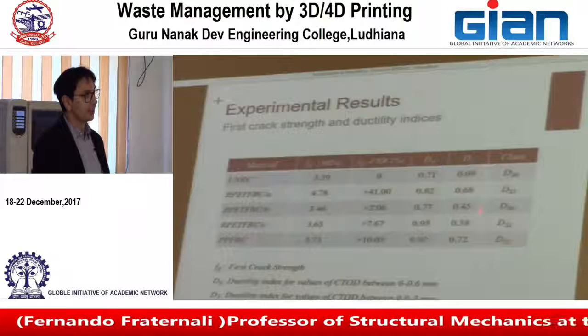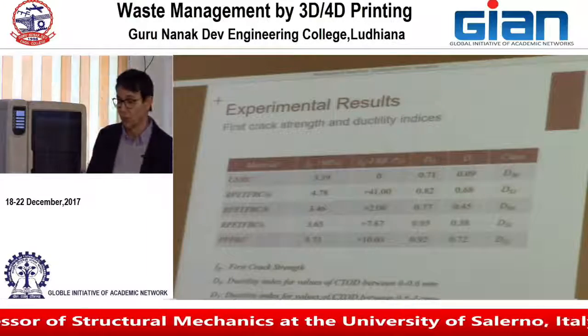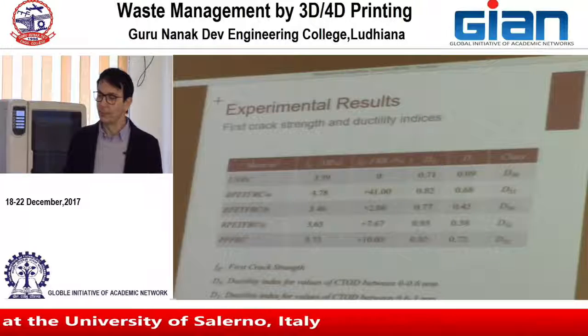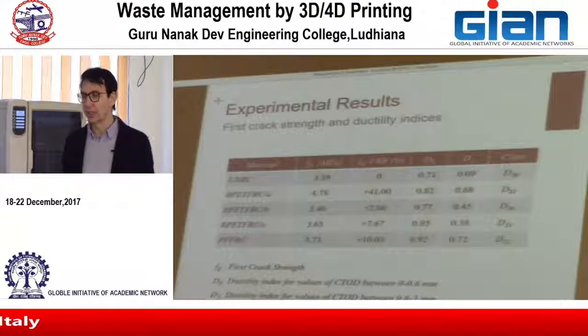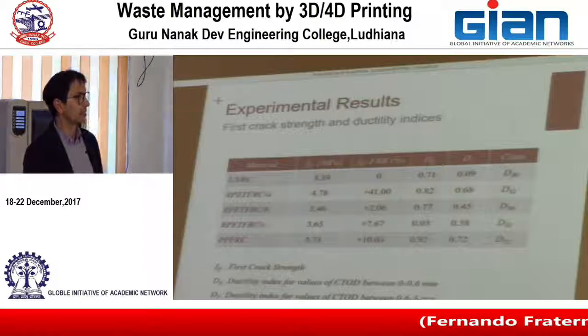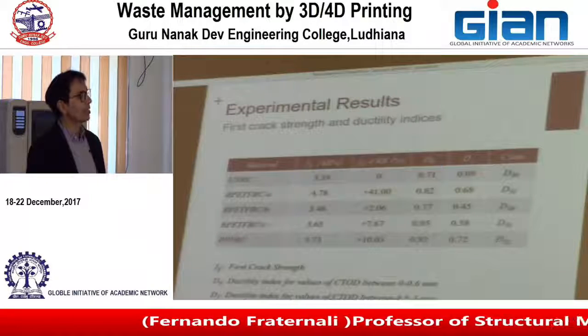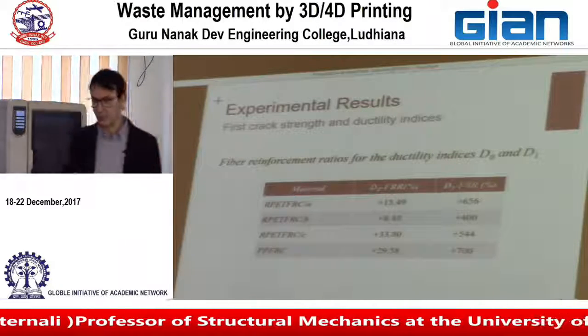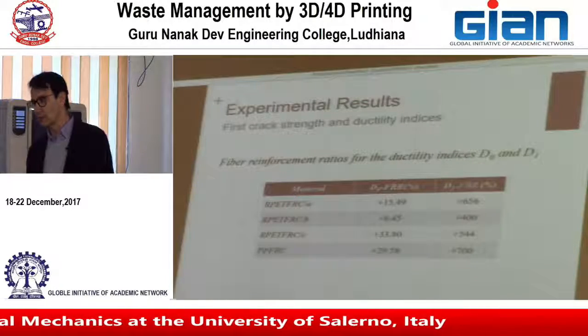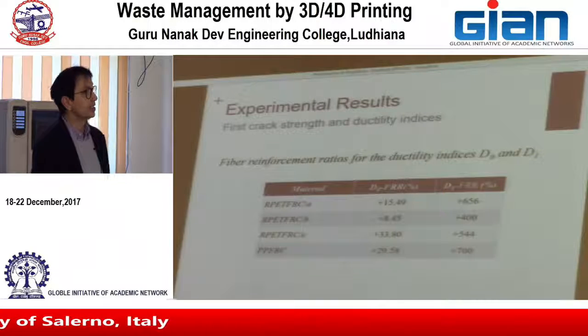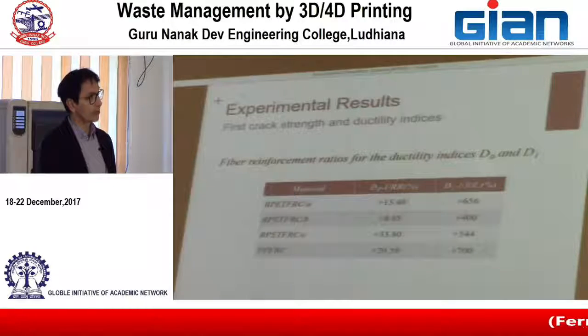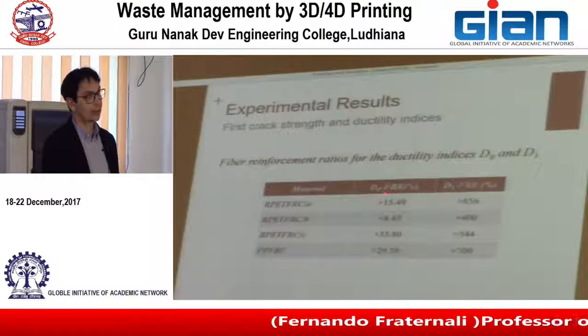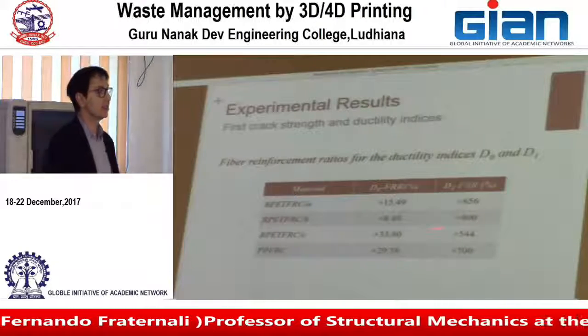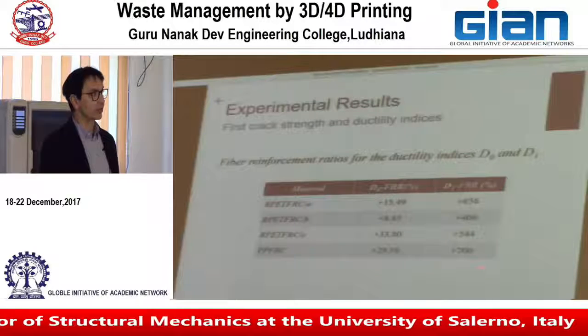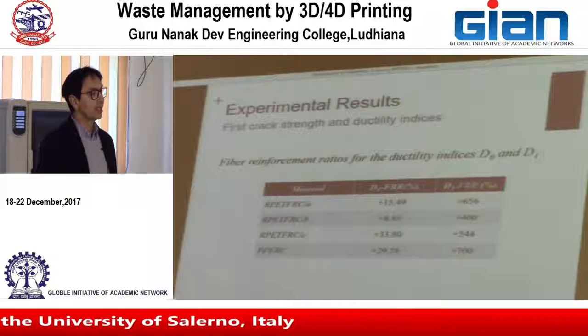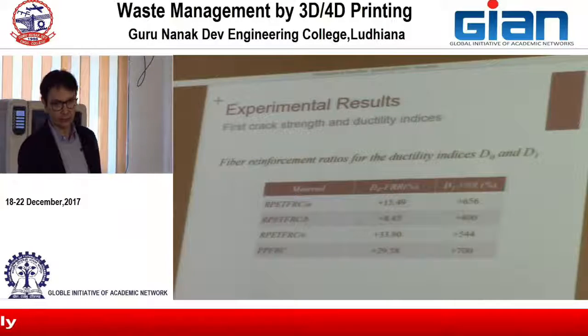So the specimens show a significant post-failure, post-cracking load carrying capacity. The increase of those two quantities over unreinforced concrete due to the fiber reinforcement is significant in terms of the first crack ductility, but is dramatically important in terms of the ultimate ductility, because in this case we have increments which are extremely large due to the fact that the plain concrete is a brittle material.